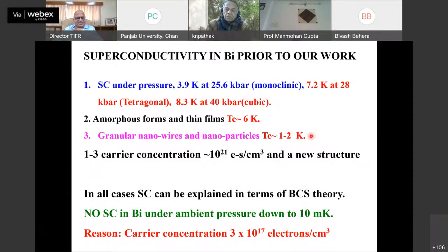And before we started working on it, a lot of work had been done on bismuth, but it's always under some pressure. It has a large number of transformations: 3.9K at 26 kilobar when it goes to a monoclinic structure, 7.2K at higher kilobar when it goes to a tetragonal structure, and 8.3K at 40 kilobar when it's cubic. So the superconductivity is there, but only under pressure, or in amorphous form and thin films, or granular nanowires. In all these cases, because the structure has changed, the band structure has changed, and the carrier concentration shoots up. You are not measuring the pure bismuth in its rhombohedral structure with the low carrier concentration. So the BCS theory can account for many of these properties, and people were happy about that.